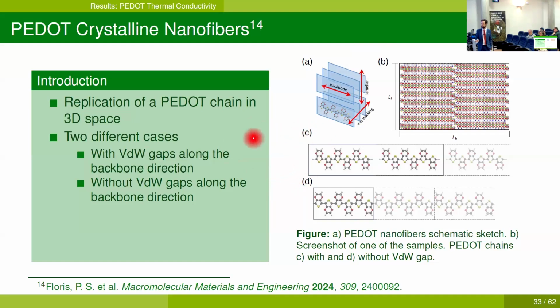So the first case in panel C represents samples which contain some van der Waals gaps here in the middle, whereas in panel D here, the simulation box is wrapped around one single chain along the backbone. And so there are no van der Waals gaps. Why do we do this? Because when we apply the approach to equilibrium technique, we define half of the simulation box will be right here or right here. And this is very different because in this case, the heat will need to jump from chain to chain, whereas here, it will not need to jump from chain to chain. So we are basically separating interchain and intrachain transport.